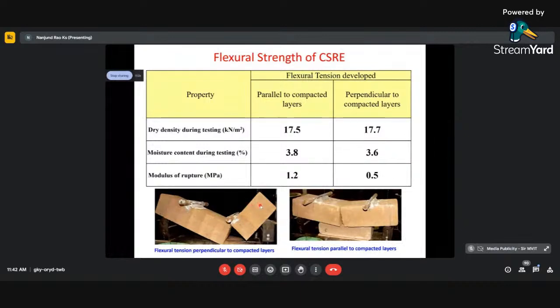You will see in the case of perpendicular to rammed layers, this is the specimen. Now you will see the parallel and perpendicular. The strengths are very different. Whenever you have the normal stress perpendicular, it is only 0.5 megapascal, but in the other direction you see 1.2. Therefore, easily showing that there is orthotropic behavior both in terms of strength and elastic properties.